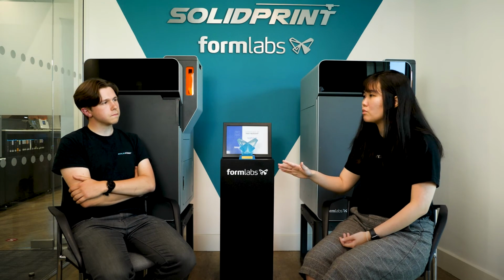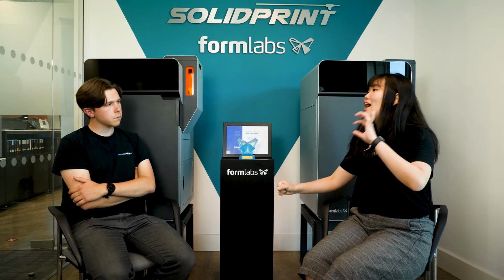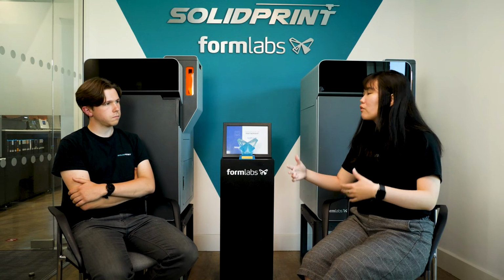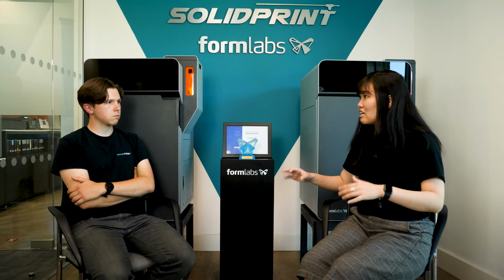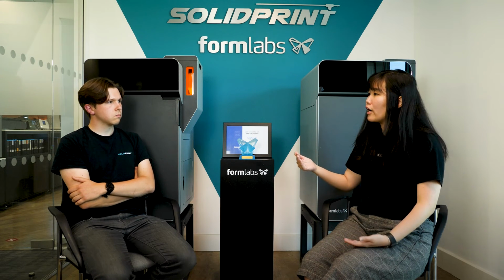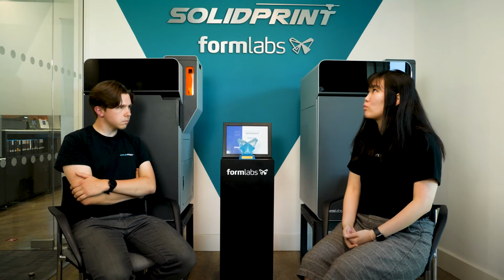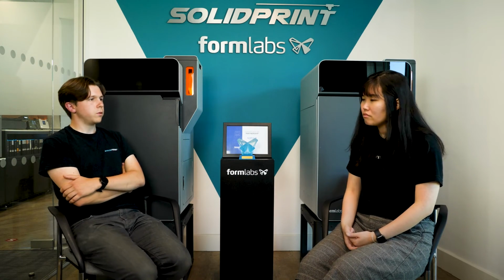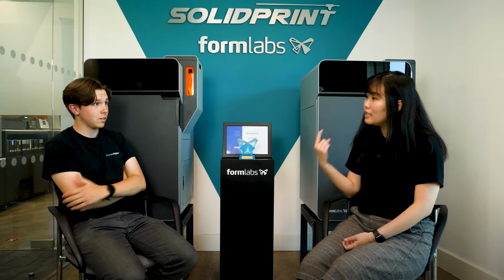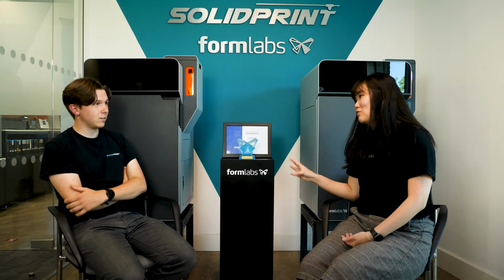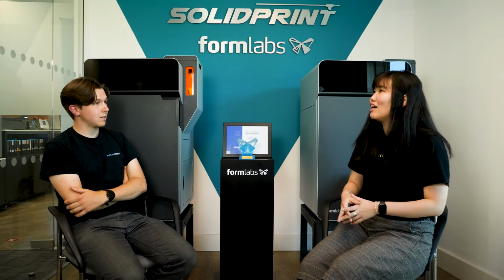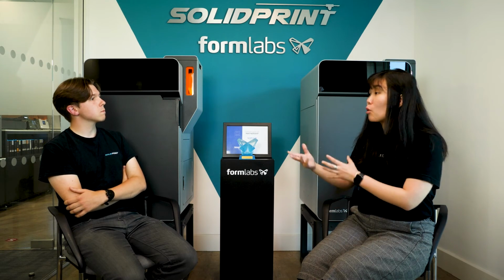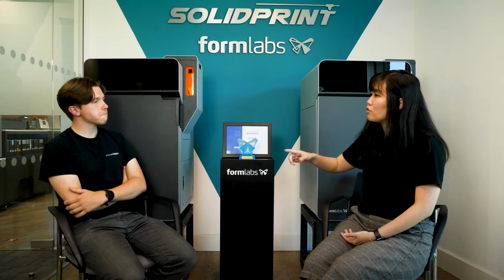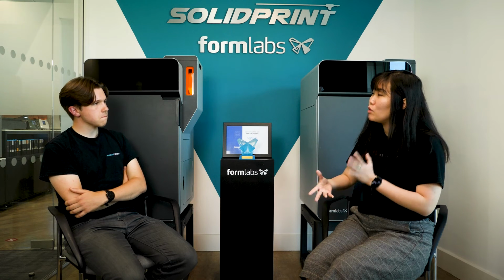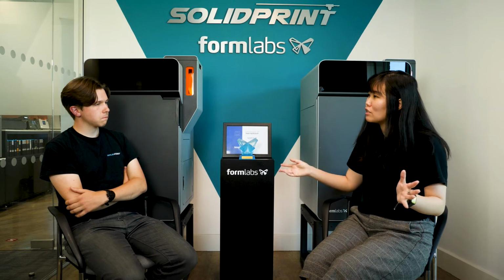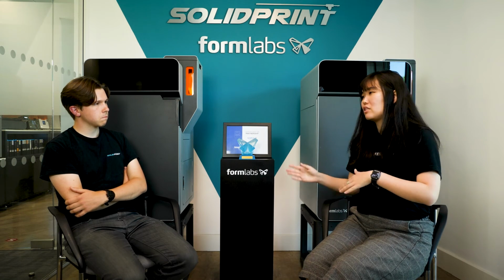Okay, yes. So obviously the longer the print, the longer the cool down time, the shorter the print, the shorter the cool down time. But there's not too much of a difference between Nylon 11 carbon fiber and, let's say, Nylon 11, Nylon 12. Nylon 12 is around 180, let's say. Nylon 11 carbon fiber is slightly higher, but it's not to a degree where the print times or cool times will change. Okay, yeah. But the actual speed of the print itself is faster. Faster, yeah. For all materials, if you are using Fuse1 plus 30W, it is the laser that's three times more powerful. So the scanning speed has improved for all materials. So the print time improvement is reflected in all materials if you're using Fuse1 plus 30W compared to the Fuse1.